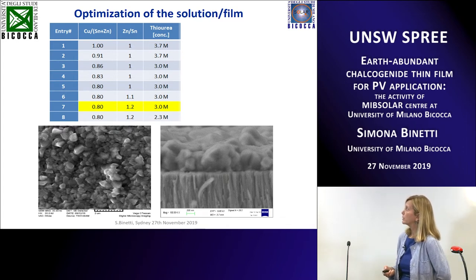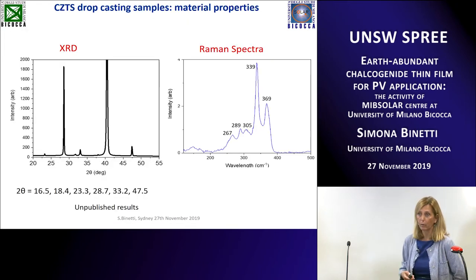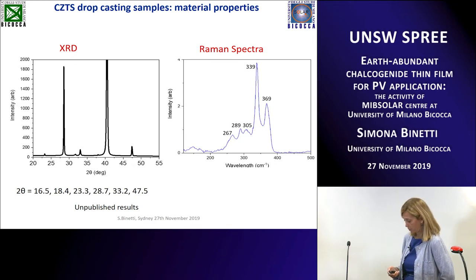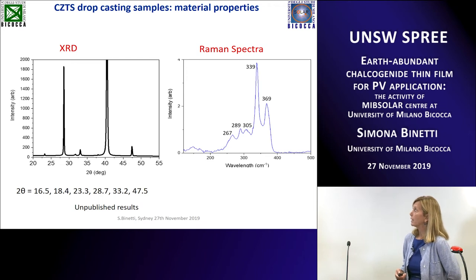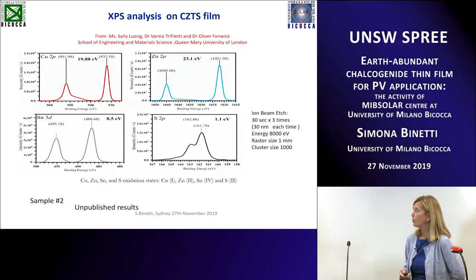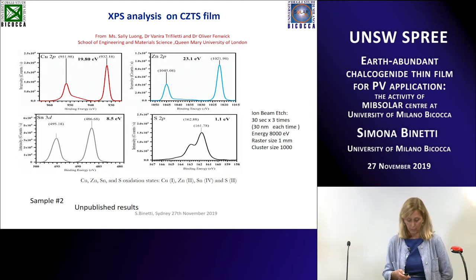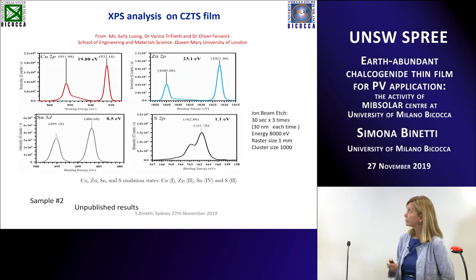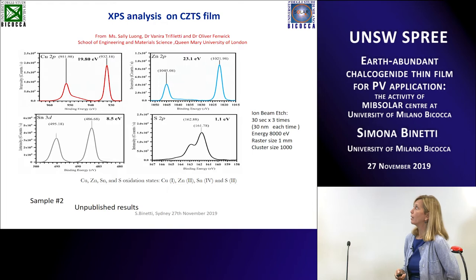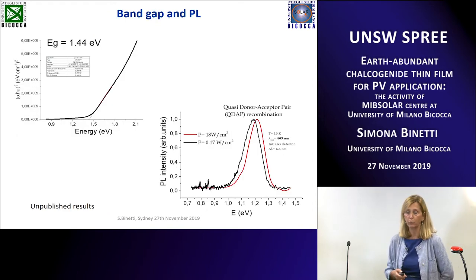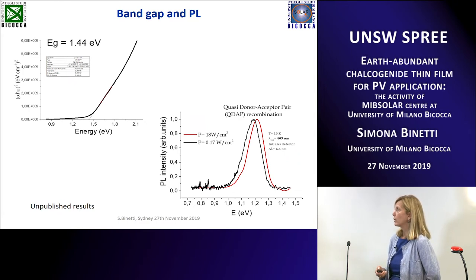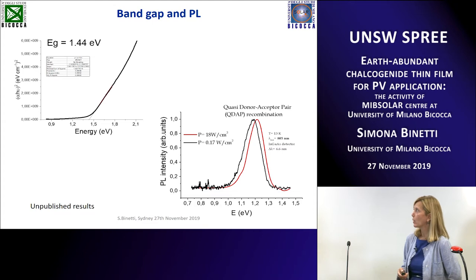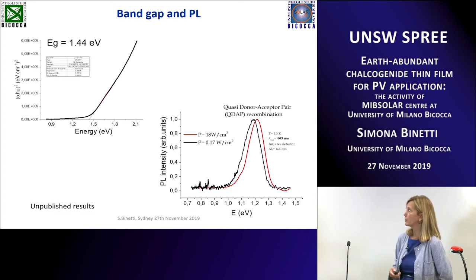About the properties of this thin film, we have quite good Raman spectra with all the signals related to Kesterite and without any secondary phases, and also the X-ray diffraction spectra are very, very good. We also checked the composition by XPS analysis, and we have seen that copper, zinc, tin and sulfur are in the proper oxidation states for Kesterite thin film. As far as the optical properties are concerned, the band gap by Tauc plot is, as expected, around 1.4 eV, and by photoluminescence we have a quite feeble signal at room temperature, but a quite good signal at low temperature with a quasi-donor-acceptor pair, and we didn't see any defect band around 0.8.